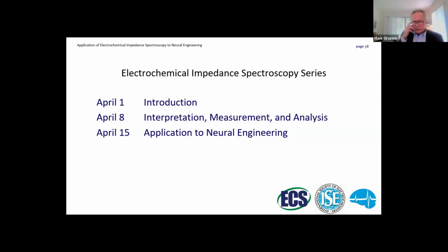Do you remember when we talked about impedance measurements, I talked about different timescales for impedance measurements. If the system is changing such that five impedance measurements taken one after the other look different, but each individual one is consistent with the Kramers-Kronig relations, then we're fine. But if the system is changing so fast that the measurement at any given frequency is seeing the effect of that change, then impedance is really not going to be a useful tool. And you'll have to look for other experimental techniques.